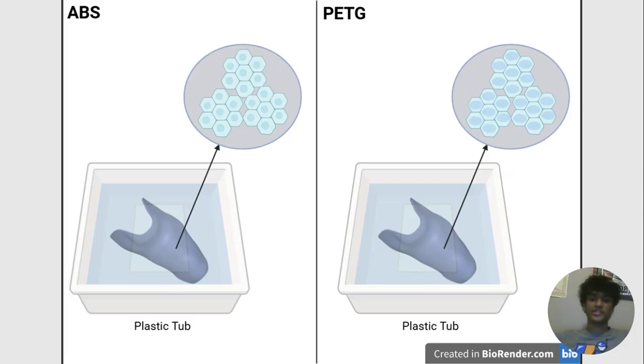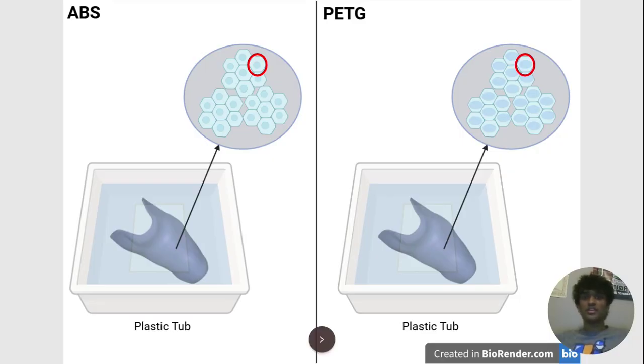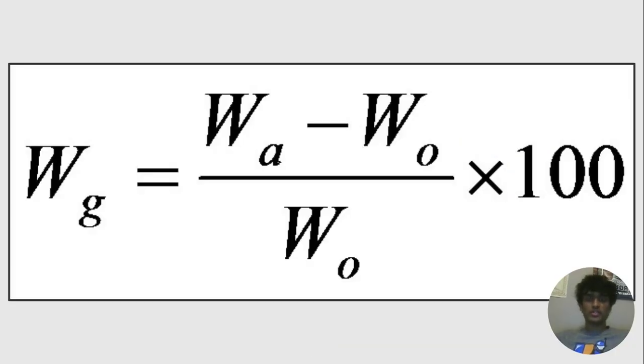Each prosthetic was placed in a plastic tub for 24 hours. The red circle shows the actual hexagonal infill, the actual plastic structure. As you can see, the blue dot represents water. And in terms of ABS and PETG, the blue dot is a lot more potent in PETG, showing that in terms of this test, PETG absorbed more water on average. In terms of calculating water absorption percentage, the mass after the water absorption and the mass before was subtracted and then divided by the initial mass and multiplied by 100.